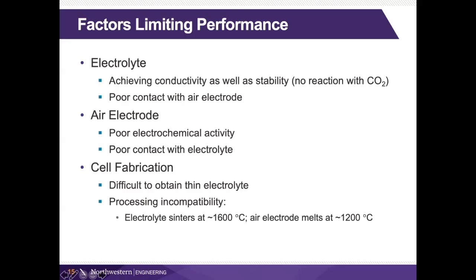One of them was achieving this high conductivity as well as good stability in the electrolyte. Another was poor contact with the air electrode. The air electrode had poor electrochemical activity and difficulty to make the cell, because this thin electrolyte is actually a challenge, because these proton conducting oxides are rather brittle, require high temperatures to process and so on. So generally a processing challenge.